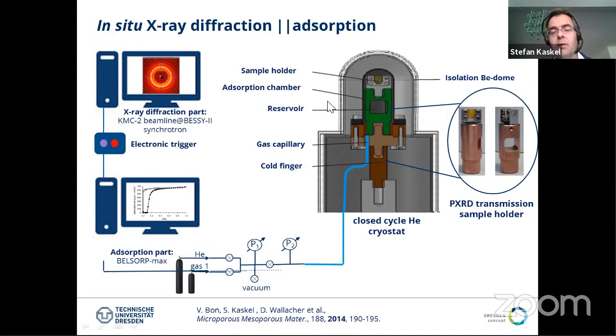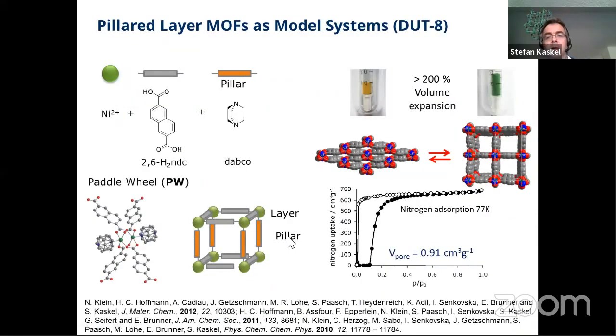And what is special about this device is basically that there is a second beryllium dome on top in order to evacuate the space in between the gas chamber and the outer environment in order to achieve a very good thermal equilibration, because of course we don't want to have any leakage here. This is also different from normal in situ X-ray or operando catalysis measurements. Here, in order to have really full equilibrium, we need to have a high thermal stability for this type of instrumentation to measure isotherms at 77 Kelvin.